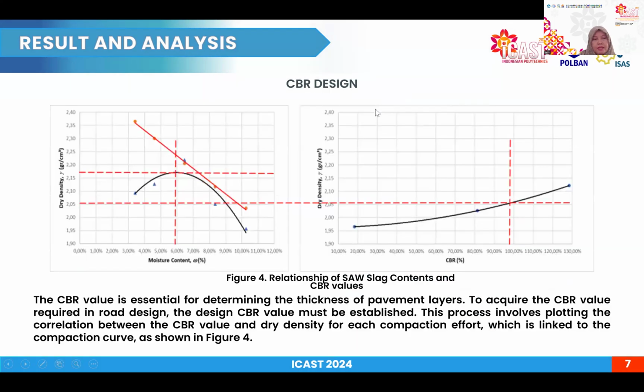And this is the CBR design. The California bearing ratio test was conducted under soaked conditions. Water was added based on the optimum moisture content from the compaction test. The CBR value is essential for determining the thickness of pavement layers. To acquire the CBR value required in road design, the design CBR value must be established. This process involves plotting the correlation between the CBR value and dry density for each compaction effort, which is linked to the compaction curve as shown in figure 4.